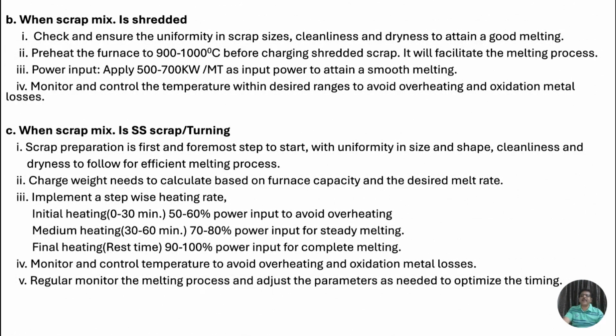When the scrap mix is shredded, check and ensure uniformity in scrap sizes, cleanliness, and dryness to attain good melting. Preheat the furnace to 900 to 1000 degrees C before charging shredded scrap. It will facilitate the melting process. Number three, power input. Apply 500 to 700 kilowatt per metric ton as input power to attain smooth melting. Number four, monitor and control the temperature within desired ranges to avoid overheating and oxidation metal losses.